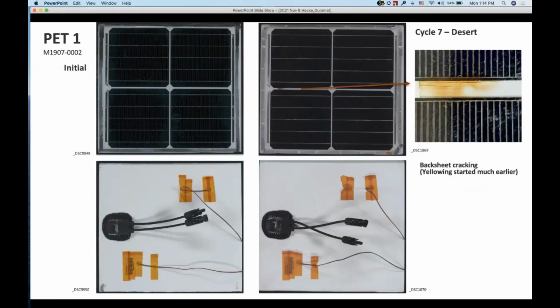So the PET one. Well, what we found initially, the 4-cell mini modules that we use, it looked good. And slowly, in time, we found yellowing on top of the junction box. And eventually, we could see cracking. So if you can see my cursor here, we've got cracks developing there, there, there. And we think about why this could be happening under the junction box.